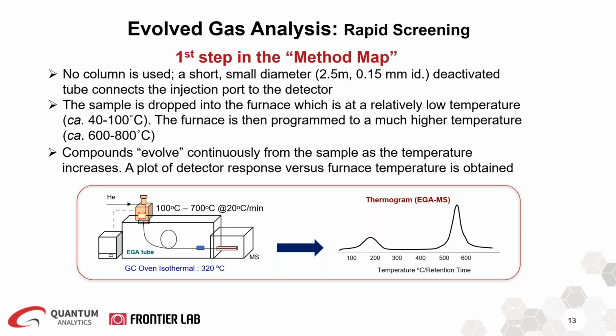To perform EGA, a short and deactivated tube is used to connect the GC injection port to the MS. The sample is dropped into the multi-mode pyrolyzer furnace, which is at a relatively low temperature. The furnace is then programmed to a much higher temperature, and compounds evolve continuously from the sample as the temperature increases. A plot of detector response versus furnace temperature is obtained, as you could see in this figure. So the x-axis is the furnace temperature, as well as the retention time, and the y-axis is the intensity.